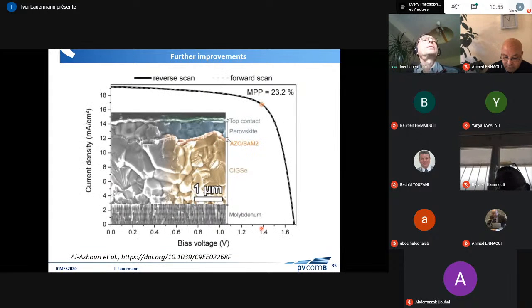Now, another material that is used for an efficient recombination junction are organic molecules, and they form just a single molecular layer, a self-assembled monolayer, or SAM. So they're very thin, they absorb almost no light, and the electronic properties can be tuned. And this is a collaboration with a group in Lithuania, and they developed this material. It has been patented by now. And so with that, the efficiencies went up.